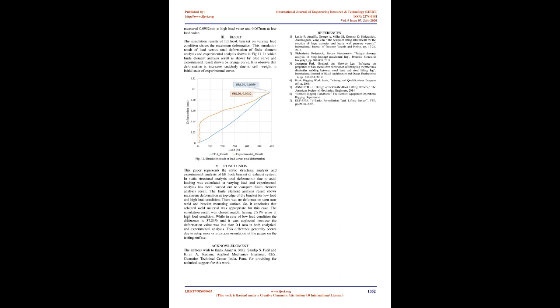3. Result. The simulation results of lift hook bracket on varying load condition shows the maximum deformation. This simulation result of load versus total deformation of finite element analysis and experimental analysis shown in Fig.11, in which finite element analysis result is shown by blue curve and experimental result shown by orange curve. It is observed that deformation increases suddenly due to self-weight in initial state of experimental curve.